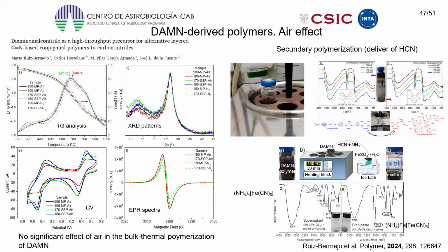All the experiments so far indicated correspond to simulation experiments of the early Earth. In addition to this work, we tested the effect of air on the bulk polymerization of DAMN. No significant differences were found between the DAMN polymer synthesized under anoxic or air conditions. However, we can observe directly that during these thermal processes, under anoxic or air conditions, hydrogen cyanide and ammonia are released to the environment.